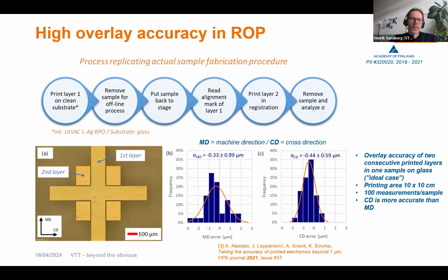And this test is really done in the authentic way, that we print one layer, remove the substrate, and replace it on the stage again, do the positioning, and make a second print. So it's not consecutive prints without touching the substrate. It's really a measure of how accurately you can print onto another layer.